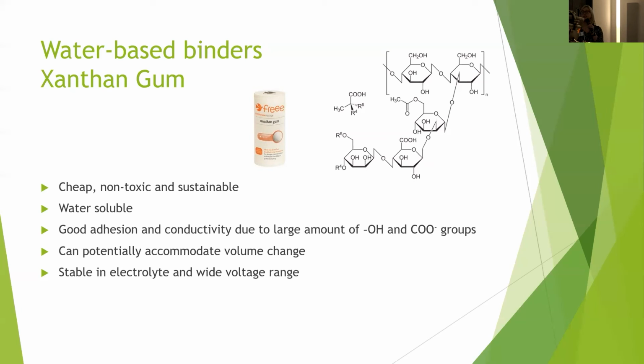And it's said that because of the functional groups, the hydroxyl and carboxyl groups, that's what helps to keep the good adhesion together. And also because of the type of bonding and its general structure, it can potentially accommodate a volume change better than PVDF. And it's also been found to be really stable in electrolyte and a wide voltage range.